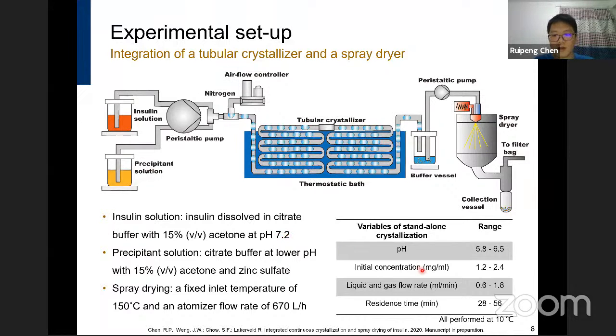This is to avoid insulin degradation. The variables for standalone crystallization are pH, which is in the range of 5.8 to 6.5, and the initial concentration, which determines the supersaturation, and the liquid and the gas flow rate, and also the residence time. And the temperature is fixed at 10 degrees C.